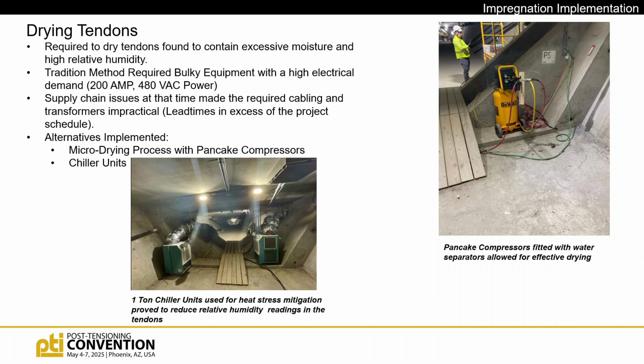and this saves the state money and actually helped reallocate funds towards other repairs that they wanted to make while we were out there. But we ended up using a micro drying system where we were able to use these pancake compressors and used moisture separators on them. We realized there's not a whole lot of air that you have to push through the tendon. And we could leave these on through the weekend, and we would come back and do another moisture test, and tendons were all dried out. And we had some 110 power that was already run through the bridge that was able to power all that. So it was a really good solution.